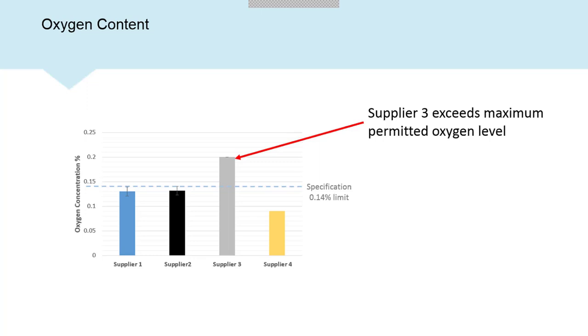So the next thing we want to look at is chemistry. So I've just generically picked out oxygen here for titanium 6-4. Obviously, oxygen is quite important. Now, the first thing to point out here is this would be a grade 23, a standard titanium grade. So your specification for the part is somewhat higher. It would be 0.2. But of course, because this is a powder, what we need to ensure is that when we're specifying powders, we're not actually buying it on the limit of the chemistry spec. We want to be buying it some way below, so we can then use it multiple times. The issue we have if we're just ordering against the standard spec is whether it's 0.14, whether it's 0.2, it's still in spec.